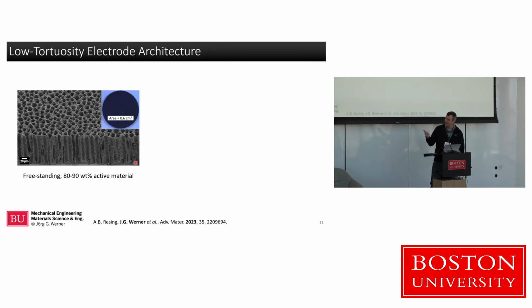Now, we adapted this process and made battery electrodes. So this battery electrode here is an electron microscope image of the cross-section here and the top surface here. So it kind of looks at a 45 degree angle here. You see these channels. You see these channel openings on one side. That's a freestanding electrode we made with that process. It's 80 to 90% charge storing material, and the rest is typically some carbon that we carbonize from the polymer to give it electronic conductivity. That's how we currently do it, and we get these electrodes.